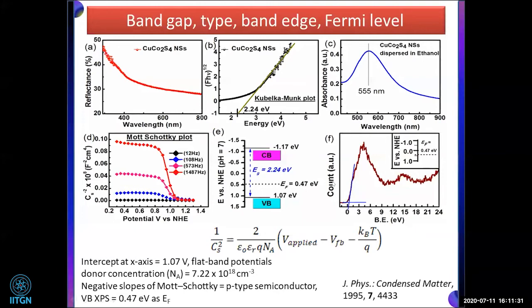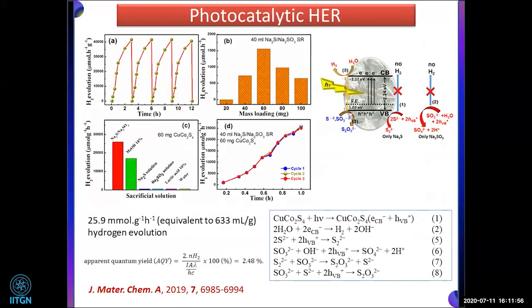We have carried out the VB XPS, and from that we found the Fermi level, which is at 0.47 electron volt. And one more thing from the Mott-Schottky, we found the donor concentration to be very high, 7.22 times 10 to the power 18 per cubic centimeter. Now this is the photocatalysis result. It is giving very good activity, almost 26 millimole per gram per hour. This is equivalent to 630 milliliter per gram hydrogen.